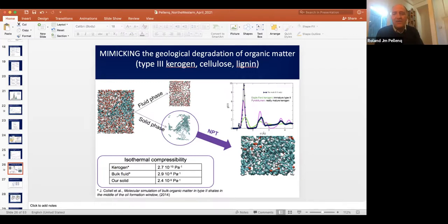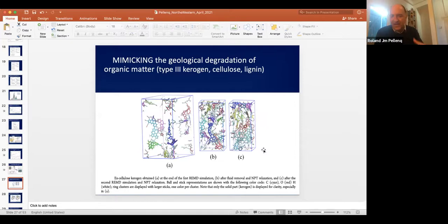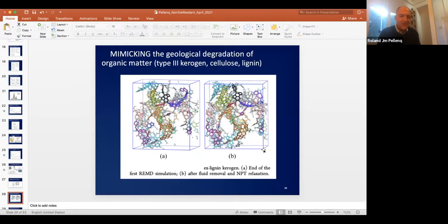All right, so now we're going to move into analyzing those textures more: porosity, density, and so on. Obviously, this is what cellulose has become when you remove the fluid. The next slide is the same for lignin, and you see that the textures can be different because lignin has bigger chunks of carbon, in the end creating bigger pores in the structure, while cellulose is more compact or denser.